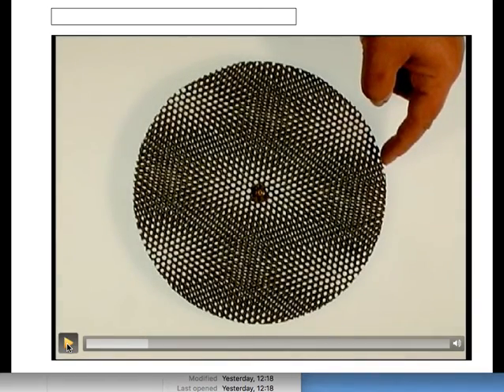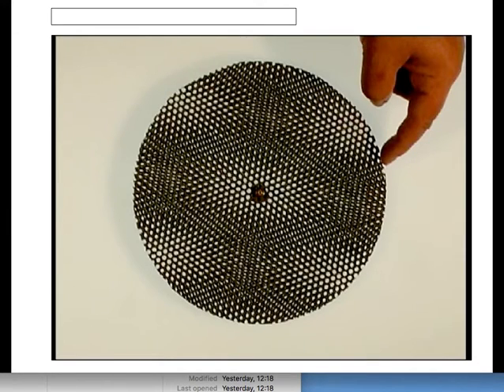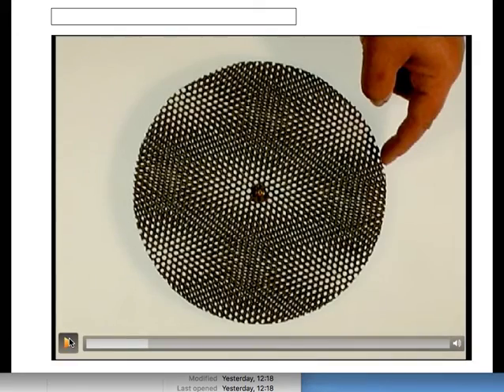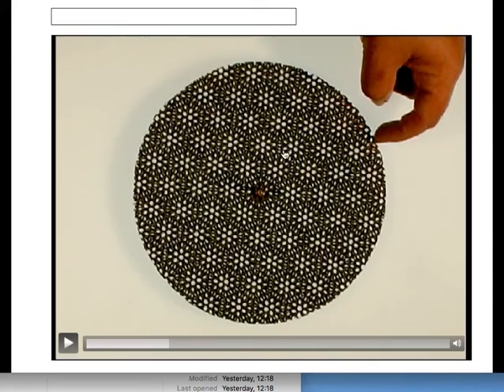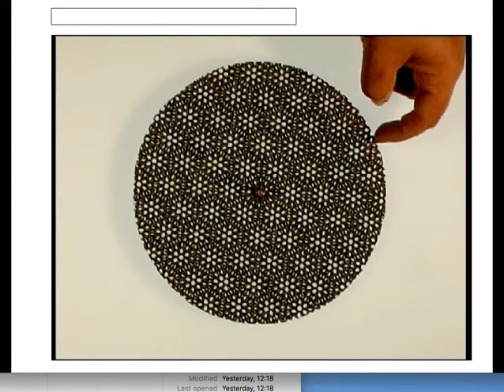Okay, now if you look at that, there are certain points where you get exact fit here, for example, between the crystal at the bottom and the crystal at the top. The light passing through the image tells you where you get exact coincidence, right? Can you see that? Okay, and if I continue, then those coincident points, for example, here and here, they actually form a pattern, right? So we'll call them coincidence sites, where the lattice points match exactly between the two crystals at a particular value of theta. And furthermore, they form a pattern, which we call a coincidence site lattice. At those points, you've got perfect matching between the two crystals, even though they are not in the same orientation. Okay. So everyone happy with that?